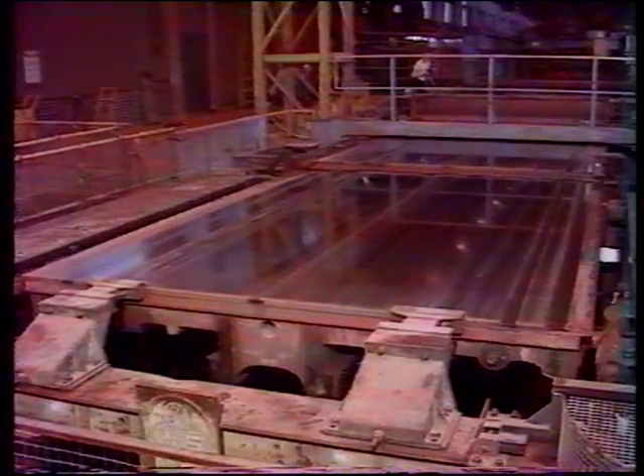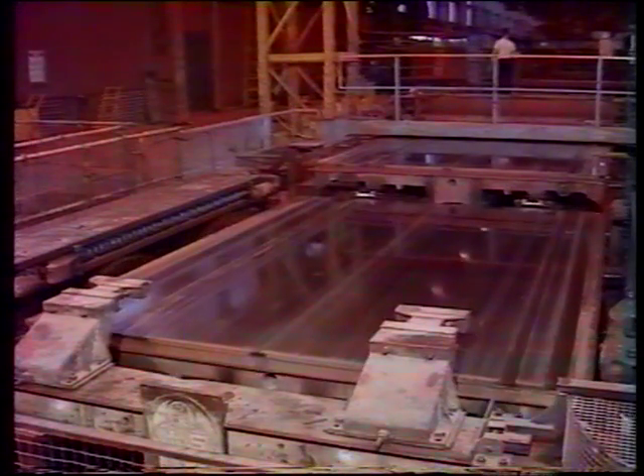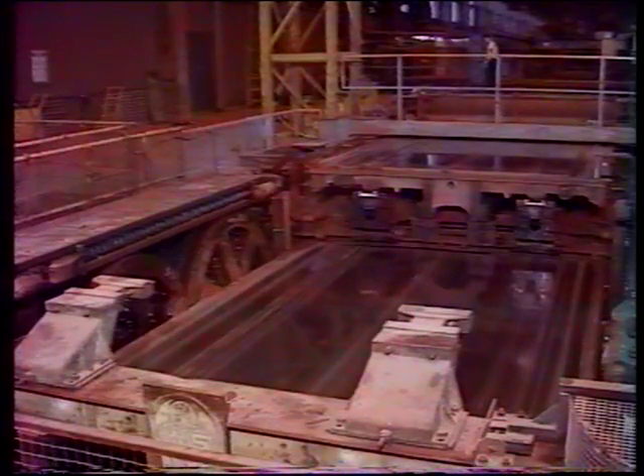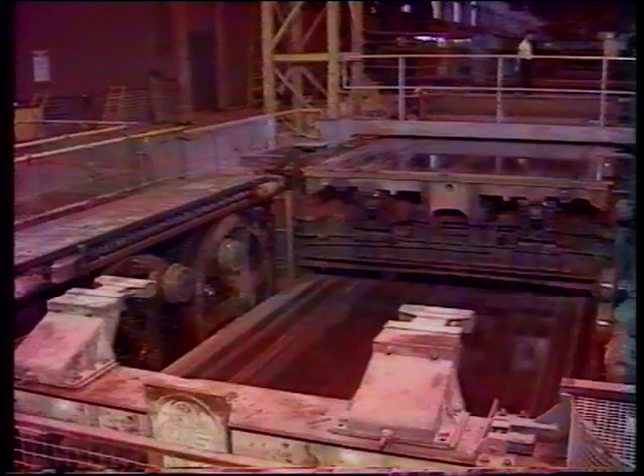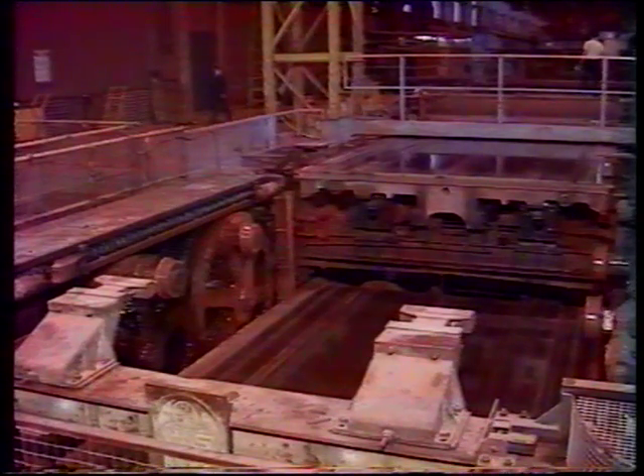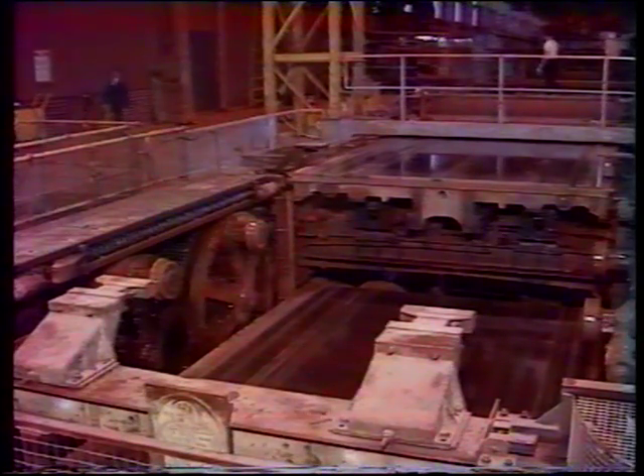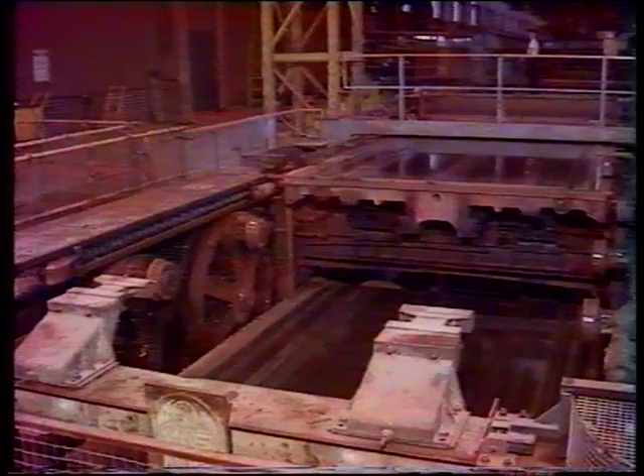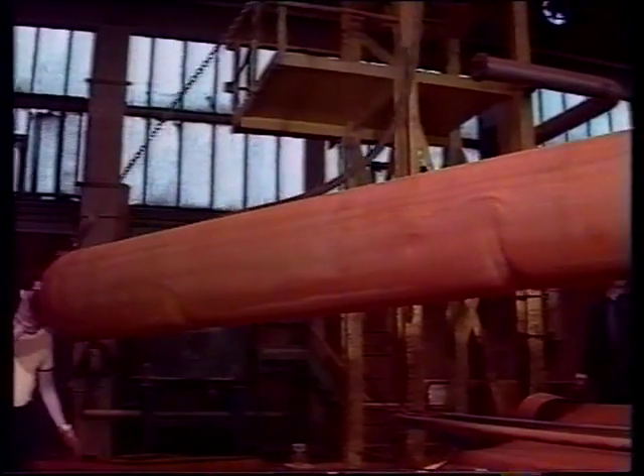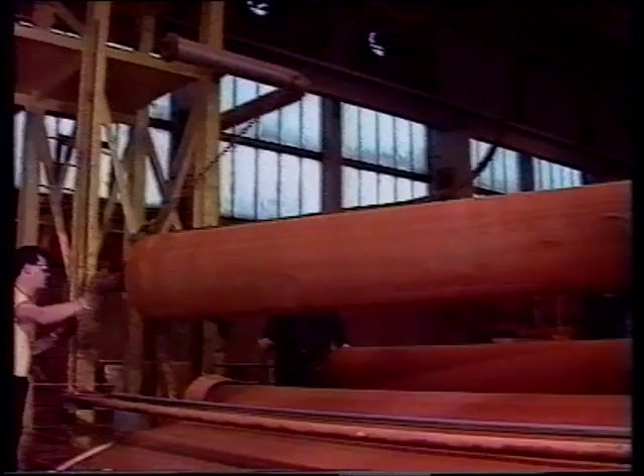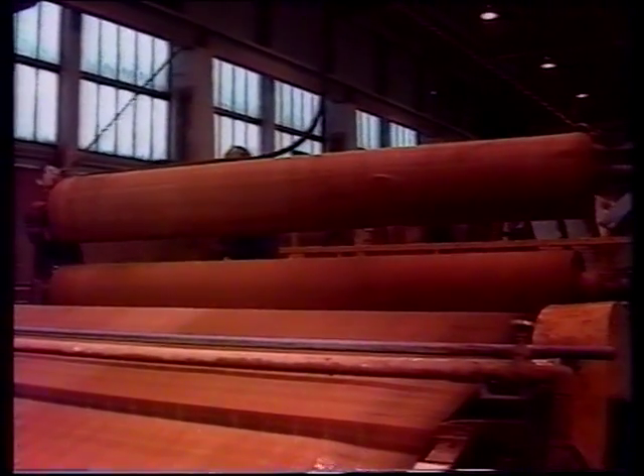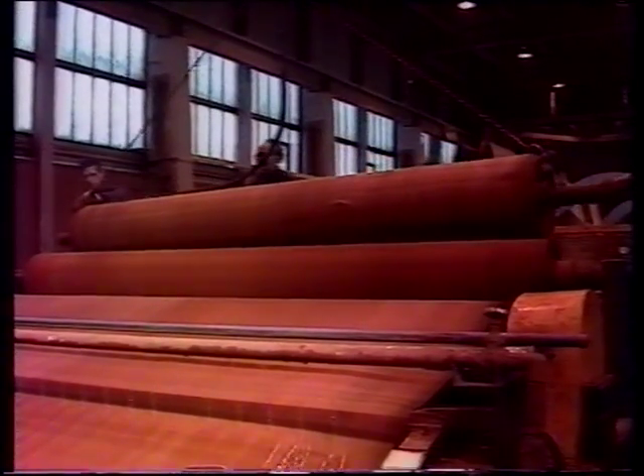At the end of the line, the tables are separated and lowered by a reverse process to that at the start, and then returned back to the start by way of driven track wheels which run under the main line. Before the glass is laid on the tables, a full-width cotton cloth is laid to support and cushion the glass. 4 cloths are in use at any one time, and a cloth lasts for about 1 month.